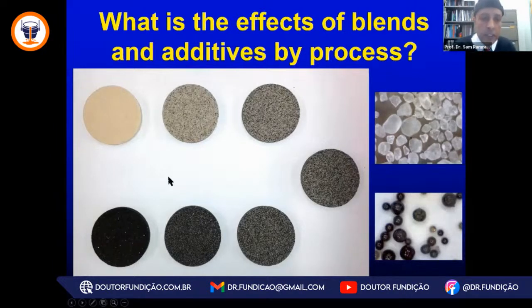So here I'm showing on this graph our standardized specimen, which is a dish-shaped specimen or cookie. That dish-shaped specimen is 50 millimeters in diameter and 8 millimeters thick. And here I'm showing one that is made up of primarily all silica sand. And then on the bottom left, it's one made up of a granular ceramic sand. And we could have a recipe that is 50-50 of the silica sand to the ceramic sand.